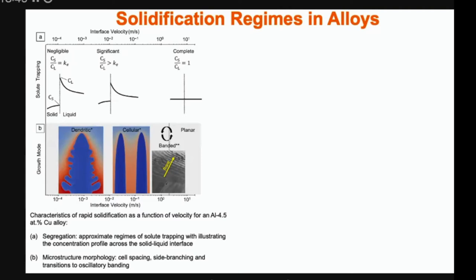As a matter of fact, at that point, you take it back to the point where thermal transfer becomes the limiting process, not mass transfer. The chemical potential is roughly constant if we assume that it's been going for a long time and allowed to reach steady state. But to be sure, there is a chemical potential gradient. And if you stop the whole process, then it'll kind of all homogenize and become constant. But the key thing is the equilibrium can no longer be assumed. So the parametrization in the phase field models to some equilibrium type of kinetics has to be abandoned.